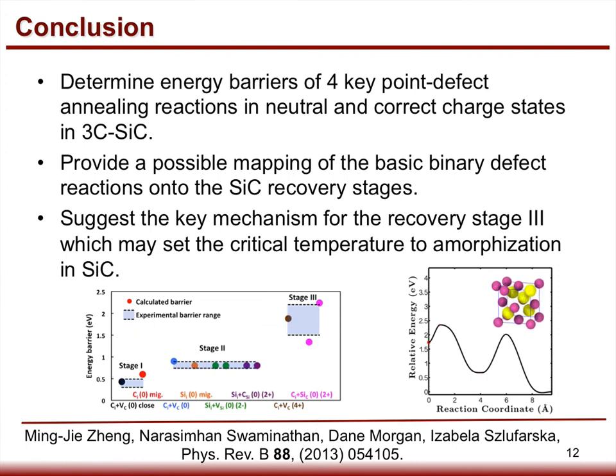In conclusion, the defect annealing mechanisms in 3C Silicon Carbide have been understood. We studied the four defect annealing reactions with different charge states and determined their energy barriers, and associated the activated defect reactions with the 3C Silicon Carbide recovery stages. We proposed the key mechanism for amorphization as the reaction in which the carbon interstitial kicks out the silicon antisite and forms the silicon interstitial. Thank you for listening to this video supplement.